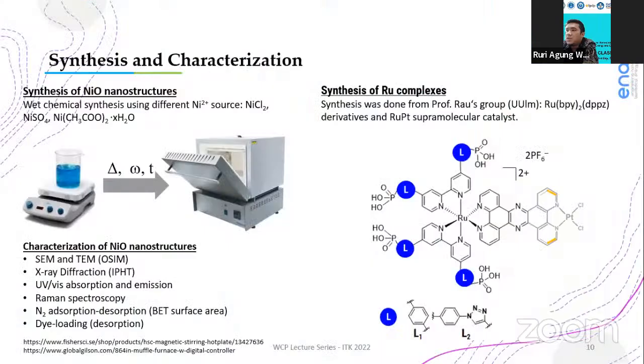Here is the methodology. We have used nickel oxide as photocatalytic materials that were synthesized by means of wet chemical methods using different nickel sources. All material characterizations were done to assess physical, optical, microstructural, as well as electrochemical properties. And the ruthenium photosensitizer here is a dipyridophenazine-based ruthenium complex, and all the catalyst was prepared by our collaboration partner from University of Ulm.